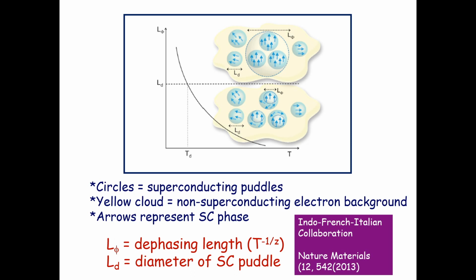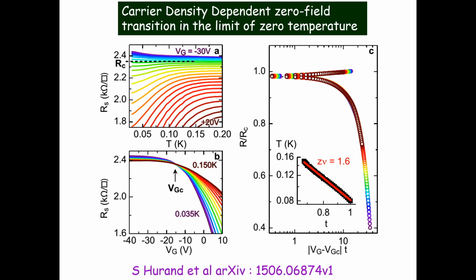But now, when this becomes very large, L sub phi actually covers many droplets. So, now one droplet is talking to the other droplet. So, here there is a regime change from here to here, and that is what probably leads to these two exponents. Now, that was a superconductor normal metal transition driven by a magnetic field. The tuning parameter is magnetic field.